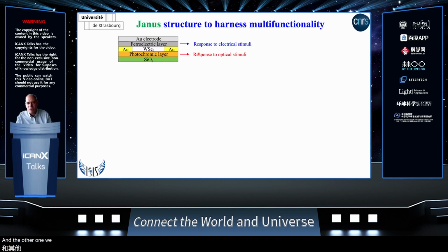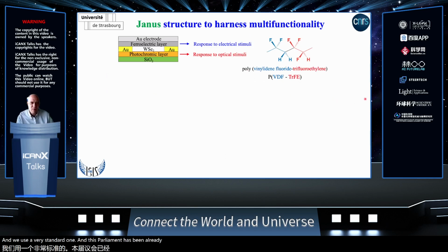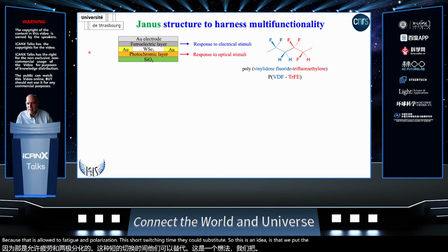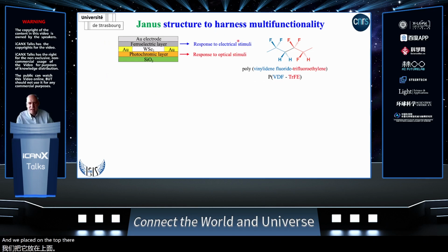Now, of course, one of the two local environments can be the photoresponsive, so photochromic, layer, and for the other one we decided to play with organic ferroelectric insulating materials, and we use a very standard one. This polymer has already been reported in the literature quite thoroughly, and it is known to be useful because of its large fatigue-free remnant polarization, short switching time and good stability. So the idea is that we put the photochromic layer underneath the tungsten selenide, and we place the ferroelectric layer on the top.